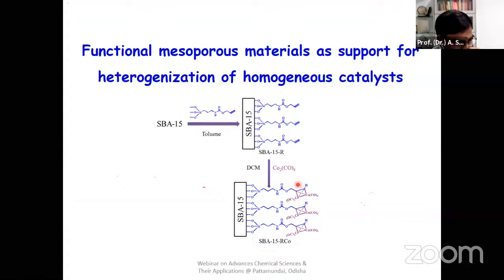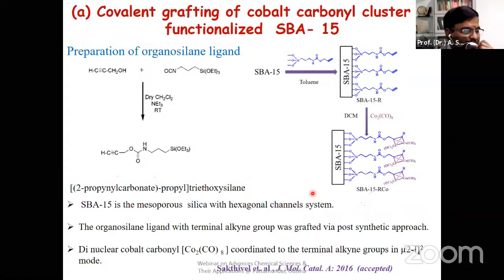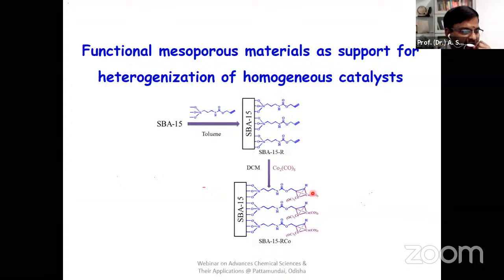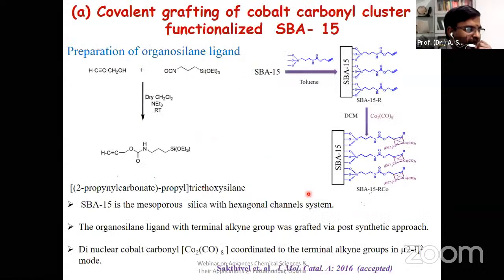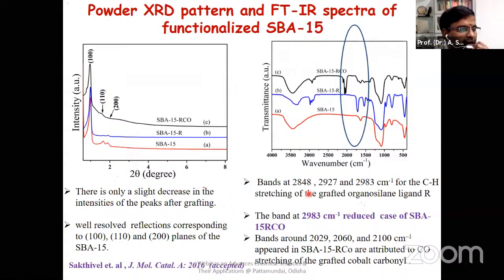Once we prepare this kind of bridging complex, the metal carbonyl can be stabilized, and with this stabilization we can handle these materials under nitrogen atmosphere without decomposing, and they can be useful as heterogeneous hydroformylation catalysts. This is the first example of a heterogeneous hydroformylation catalyst which we have shown as a potential application. The presence of metal carbonyl you can confirm from your FTIR spectra. Once cobalt carbonyl is loaded, we can see a strong intense band around 2100, which supports the presence of the carbonyl band.